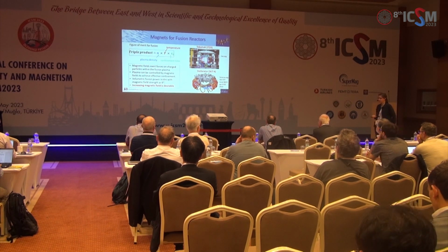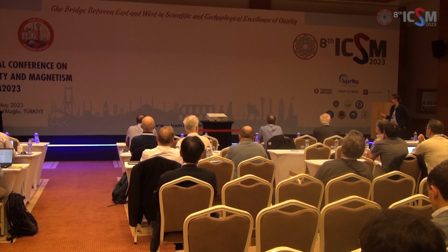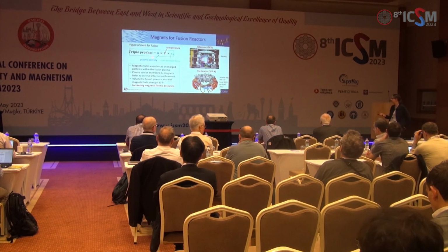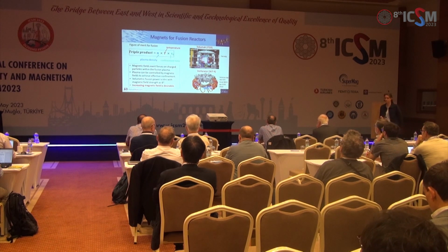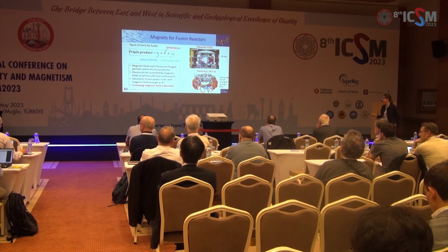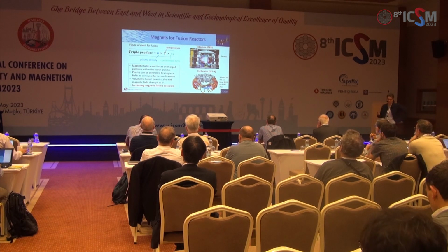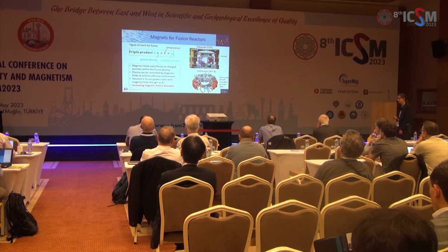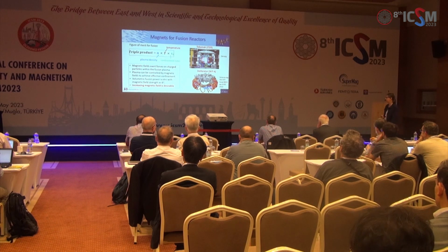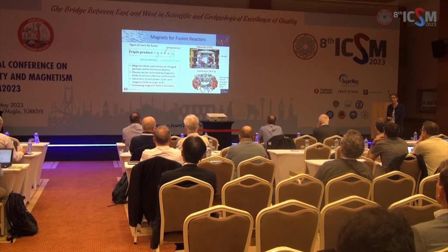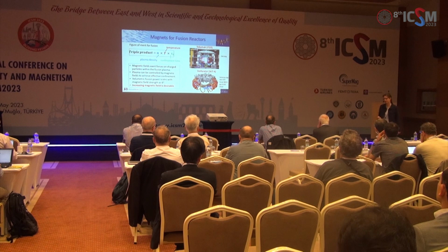In order to get fusion to happen, you need a high density of the ions in the plasma, so that's the N in this equation. You need a high temperature, and we're talking about 150 million degrees C, so very, very high, and we need to confine it for as long a time as possible. So the magnets are there to make the plasma dense enough and to confine that dense plasma for long enough for fusion to happen. We can't use real materials for this because the temperatures we're talking about is 150 million degrees C. We're never going to be able to get a material close to that kind of temperature.